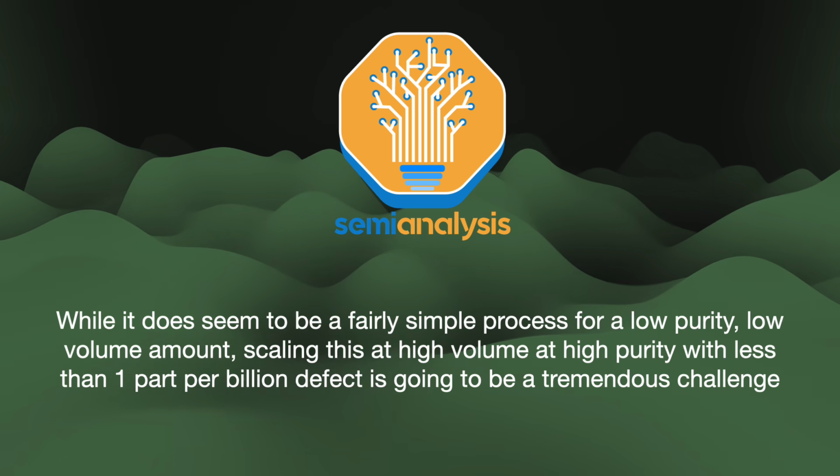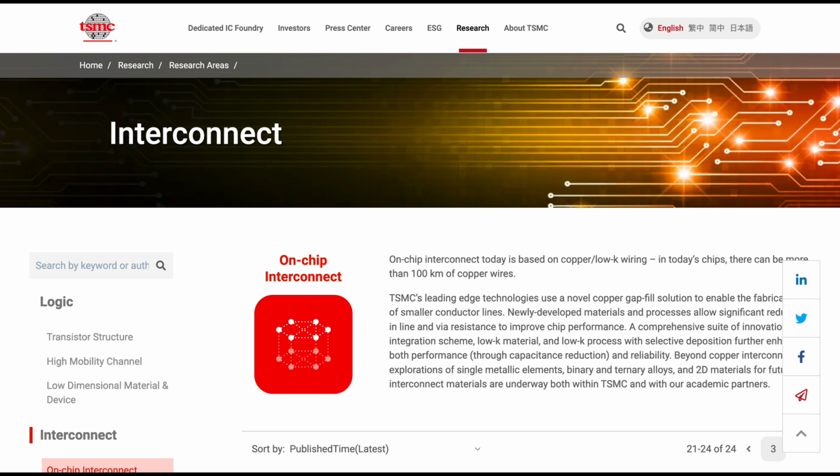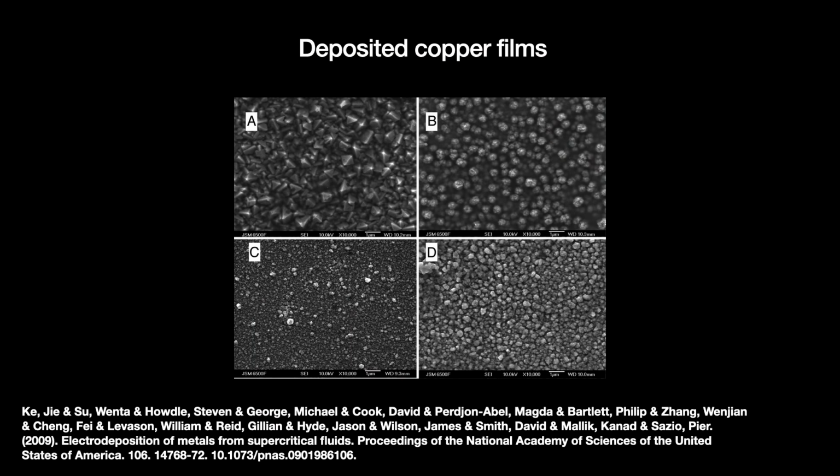Dylan has a very good point. TSMC has said that a single integrated circuit can use over 100 kilometers of copper wiring. They produce billions of chips every month. To me, this is the biggest issue. Any room temperature superconductor will be a complex alloy, and those tend not to scale. How can we integrate it into the existing process flow?